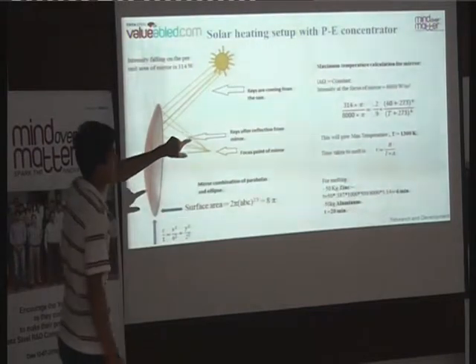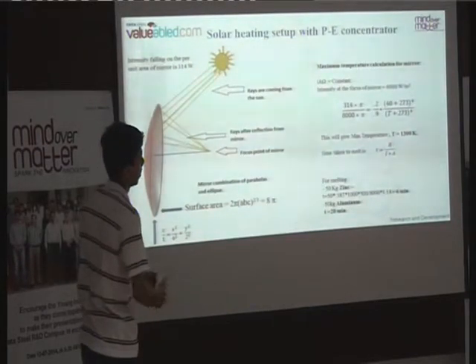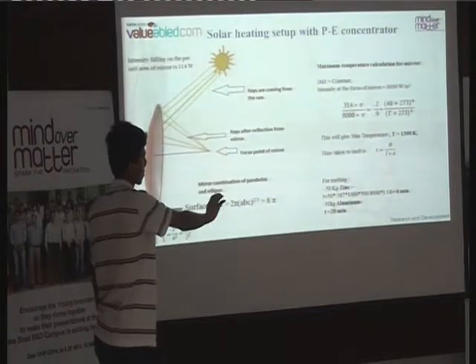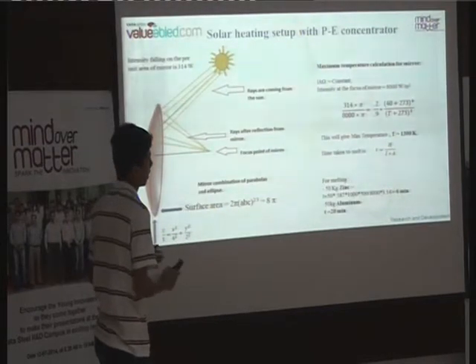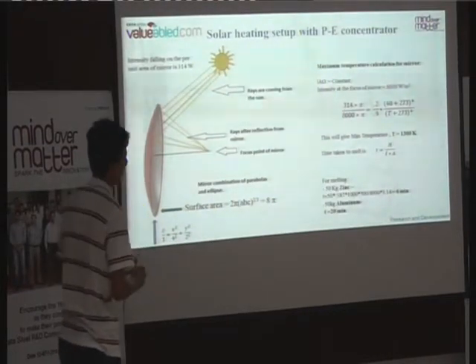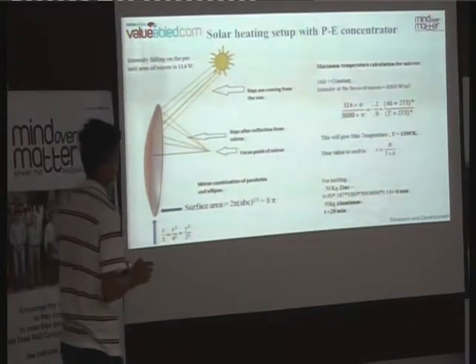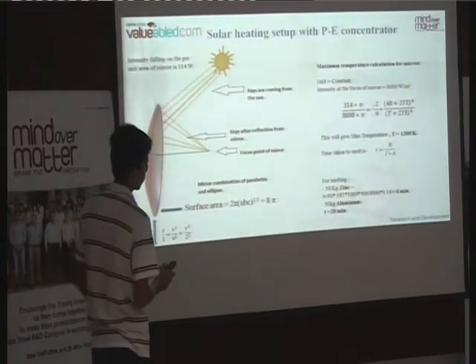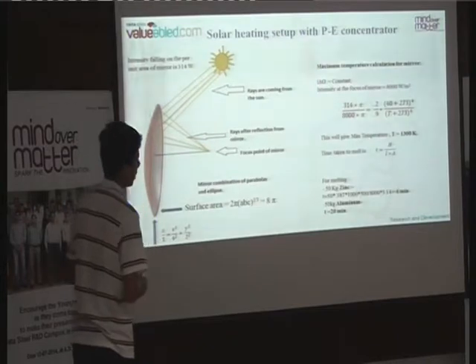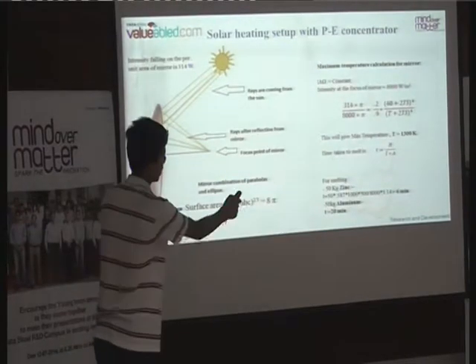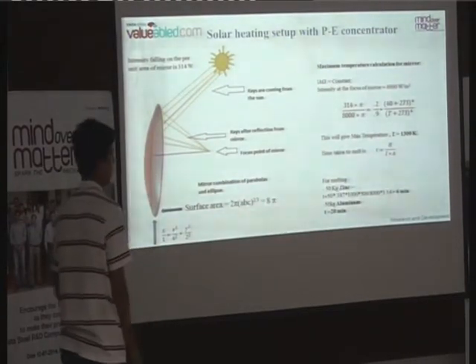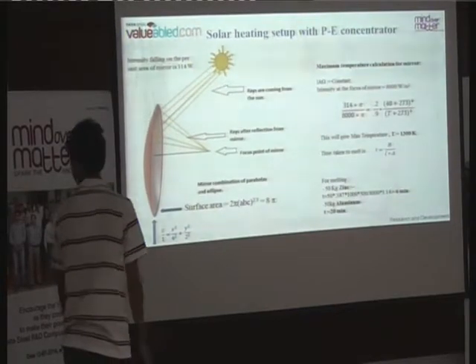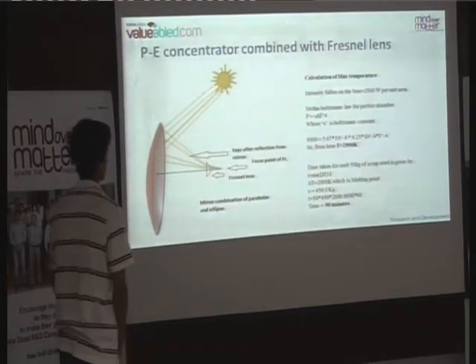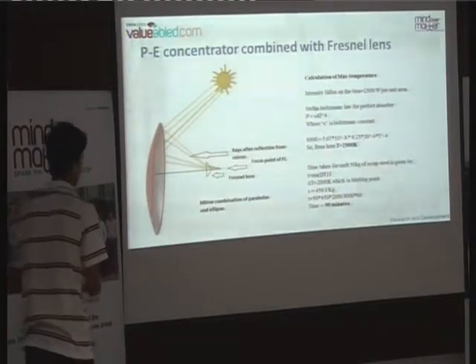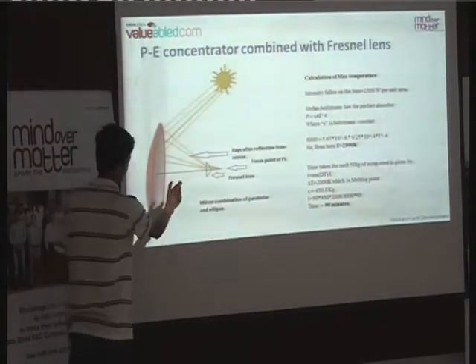From the work in this program, we found that the maximum temperature is 1300 Kelvin, and at 1300 Kelvin we can melt zinc and aluminium. For melting 50 kg of zinc, the time taken is 6 minutes, and for 50 kg of aluminium, the time taken is 20 minutes. And this part is the combination of a mirror and a Fresnel lens.